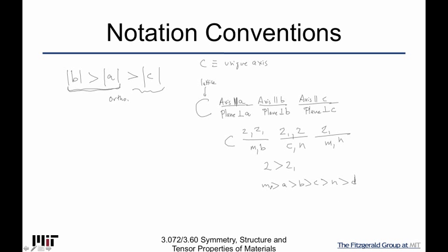And so that means that a mirror plane would dominate over a glide, but then you have a hierarchy of glide planes in the notation. So if I were to apply those rules to here, this would result in 2 over M, 2 over C, 2_1 over M. And that would be the notation that we would use in that case.